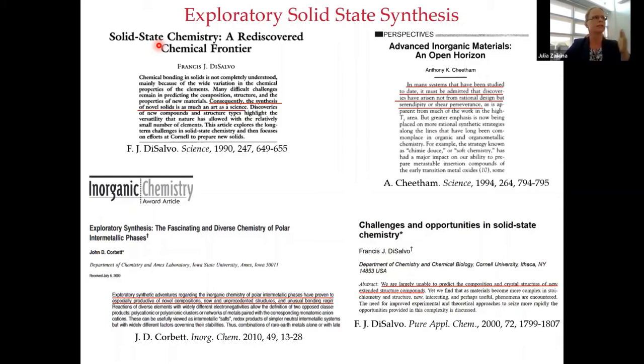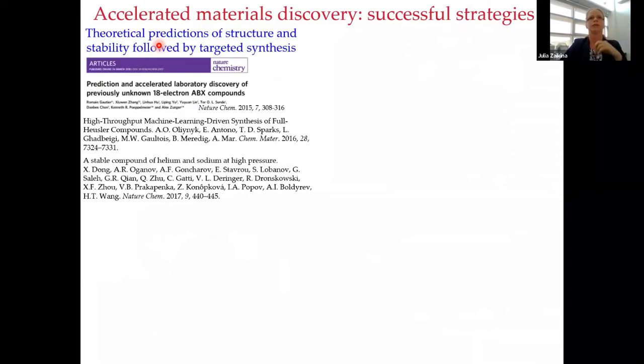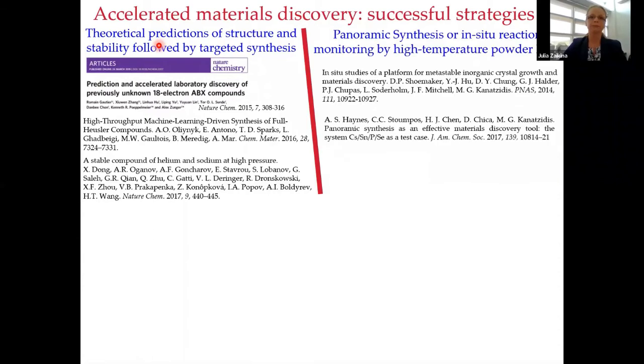I feel that in the recent 10 years or so, there was a paradigm change in the way we think about solid state synthesis. These days we have computational methods which allow us to predict whether a particular compound is stable or not, way before we start making it. We also now have high temperature powder X-ray diffraction, which has become more available to researchers. This way we can track what is happening with our materials when we increase the temperature, because solid state synthesis generally happens at several hundred to 1,000 degrees Celsius. Yes, we need very high temperatures.